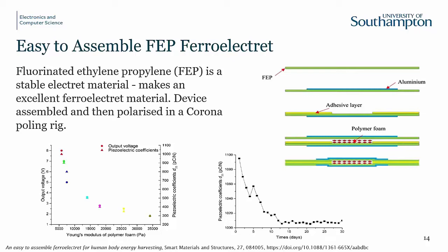And here we'd basically take a FEP film with an aluminium electrode and sandwich these together with a foam insert. Now I've shown it as a sort of discrete foam insert, but in reality that foam could extend all the way along, and you can replace the foam with a textile. The foam insert or the textile is essentially acting as a mechanical soft spacer. So if you compress this, the textile or the foam compresses and you get the ferroelectret effect.